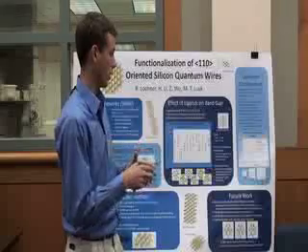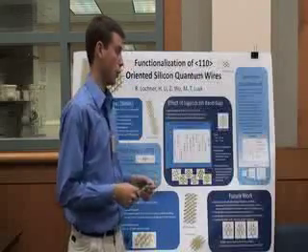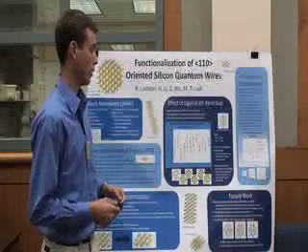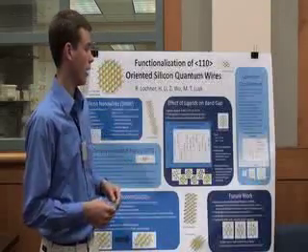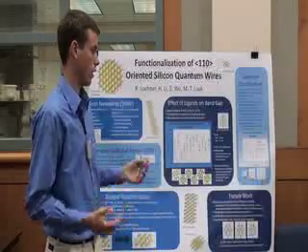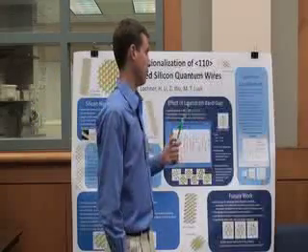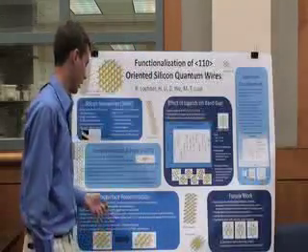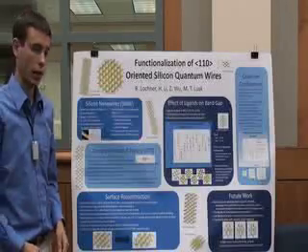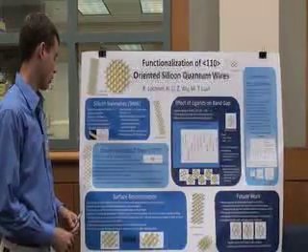So when the wire gets on the order of the exciton Bohr radius, which is about 5 nanometers, the electron and hole pair are confined, and your HOMO and LUMO levels separate. You get a larger band gap, and so that's interesting.